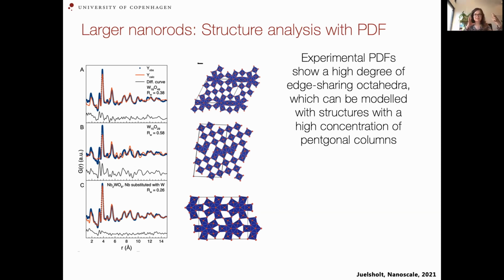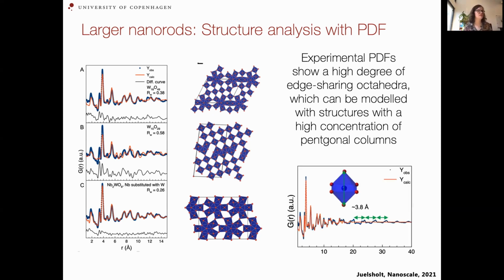So when we analyze things like this, it's important to know the limit of information that is in the PDF and how much we can get out of it. And that's something we're working on a lot, also using statistical methods. But what we found was that we can conclude that these structures have a high concentration of these pentagonal columns, where we have these octahedra arranged in these flower-like structures here. So we can get at least an idea of the structural motifs that are important in the material, and then we can start analyzing that in more detail and correlating with properties. And Mikkel also analyzed the size of the rods with this PDF, but we'll skip that.